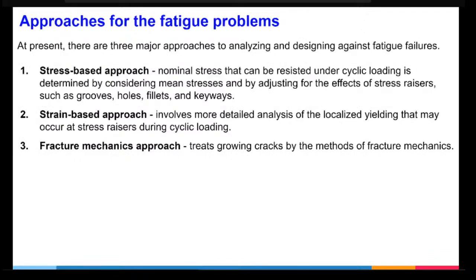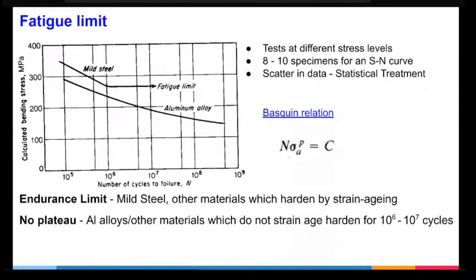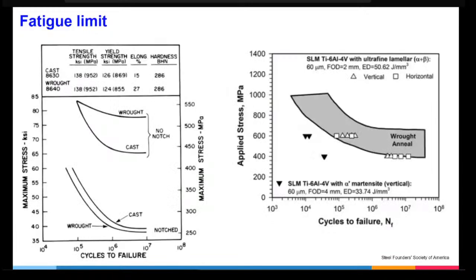So this is how one can actually plot the SN curve. But if you look at how the additively manufactured component will fit into this, most of the AM components will show inferior behavior. When I say inferior, the fatigue limit is not the same as what you see with the baseline or conventionally processed material. For example, on the right hand side, this is a wrought annealed specimen fatigue paradigm. The additively manufactured components are not actually meeting this. Some of the AM printed components, for example, Ti-6Al-4V SLM printed component, which is printed vertically, is seen to have a lower fatigue limit.